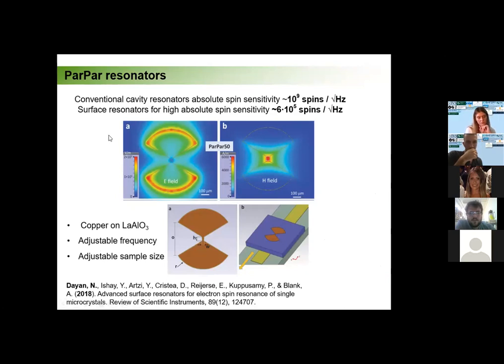So in the surface resonators, like I said, we put all of the magnetic field in this antenna-shaped structure, and it concentrates the magnetic field in this small red place, which is around 100 micrometers. And by changing the shape of this parpar, we can control the size of the sample. It can be 10 micrometers or 20 or 50 or 100, even 1 micrometer.